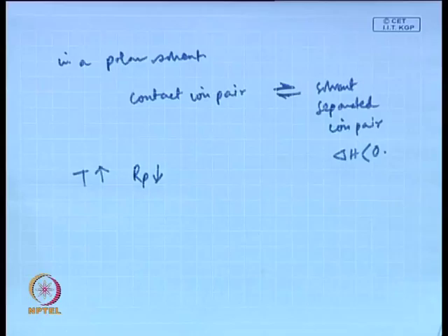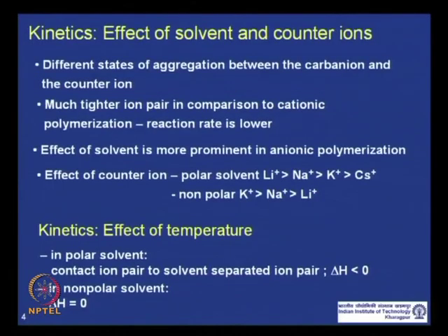In nonpolar solvent, basically there is no solvation. So, del H is 0. So, basically the temperature has minimal effect in terms of reaction rate. But sometimes what happens in case of nonpolar solvent is the aggregation of the initiator molecules, for example, like butyl lithium. We just talked about that in nonpolar medium butyl lithium could be existing in an aggregated form.